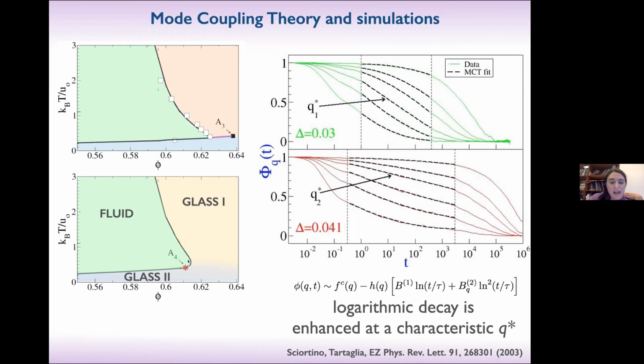So if we then are able to calculate the A4 singularity correctly, and this we can do in simulation and theory, where we study exactly the same model. It's not the same in experiment, unfortunately. We can go much, much closer to the A4 than to the A3. And in fact, when we did the simulation for the expected well width that is 4% instead of 3%, you see that now we have a logarithmic window that is much, much more enlarged. We have 4 decades of logarithmic decay at a given Q vector.